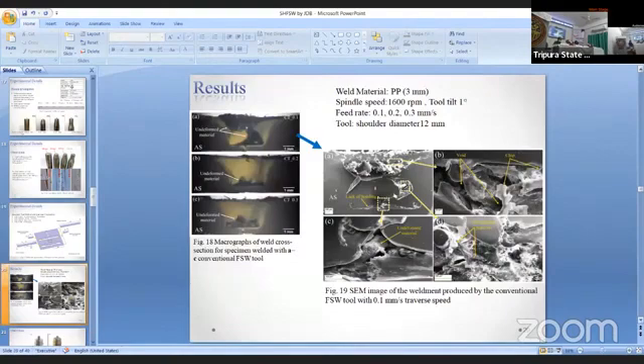Now, if we talk about the weldment produced by the conventional friction stir welding tool, we have seen that the heat was not sufficient to soften the material, as I've already mentioned. So what happened? Undeformed material was observed. As you can see in figures A, B, and C, these are the macrographs of the weldments or the specimens. These are welded with the conventional FSW tool, and at different feed rates, of course.